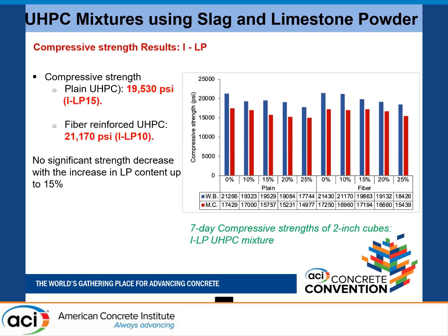We have observed no significant strength decrease with the increase in limestone powder content. We varied the limestone powder content from 0 to 25% replacement of cement, only cement. But we have not seen a significant strength decrease. That means limestone powder is interacting properly as a mineral filler in the presence of slag. These are preliminary investigations just to present what we are doing. It's ongoing work, and a lot of work is still pending.